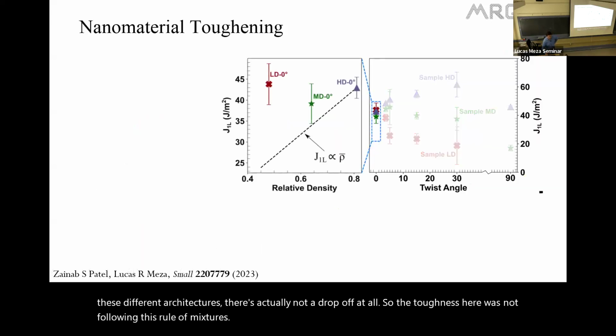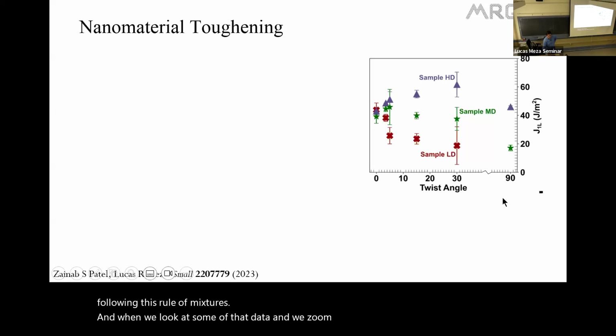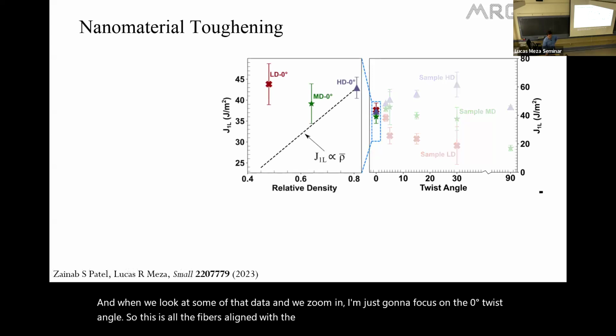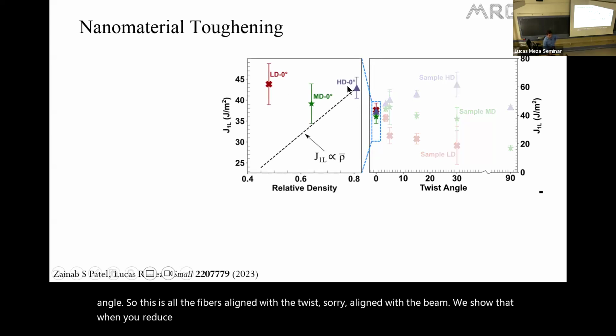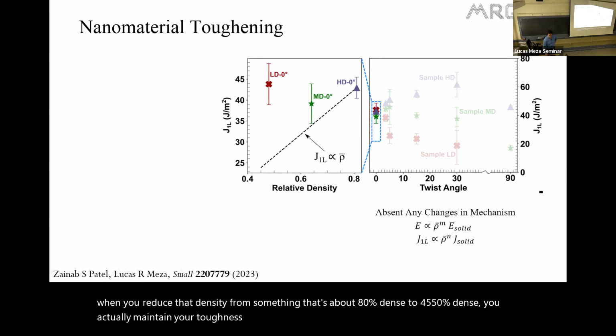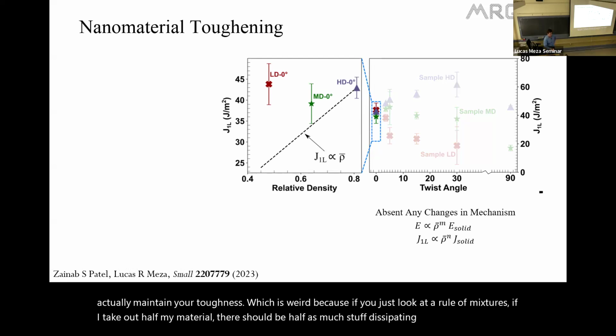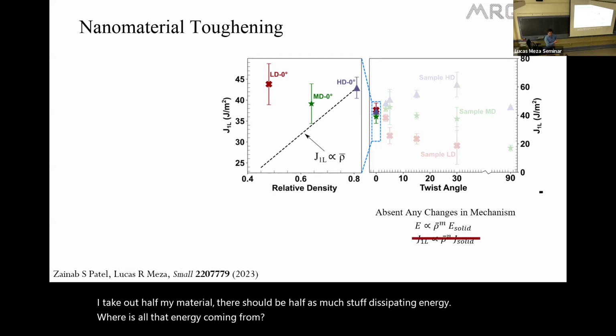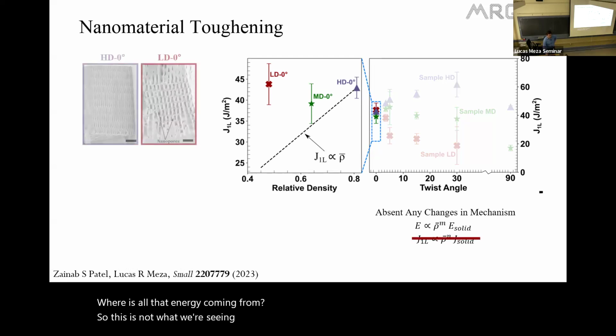And when we look at some of that data and we zoom in, I'm just going to focus on the 0 degree twist angle. So this is all the fibers aligned with the twist, aligned with the beam. We show that when you reduce that density from something that's about 80% dense to 45, 50% dense, you actually maintain your toughness, which is weird. Because if you just look at a rule of mixtures, if I take out half my material, there should be half as much stuff dissipating energy. Where is all that energy coming from? So this is not what we're seeing. I'm not seeing any sort of a rule of mixtures.